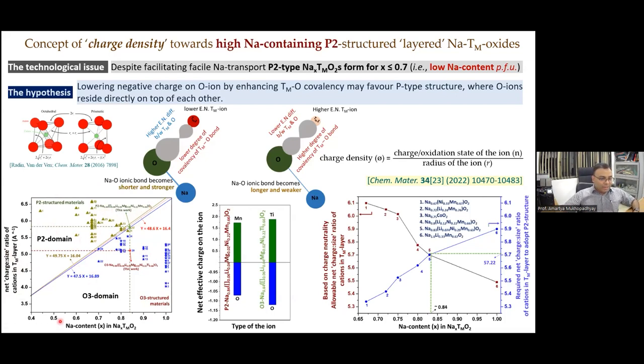And we found that for the same sodium content, a higher charge to size ratio leads to a P2 type structure and a lower charge to size ratio leads to an O3 type structure, which agrees with our hypothesis. Now, again, DFT calculations by Professor Abhijit Chatterjee's group revealed that if we design two materials which are more or less the same in terms of the composition, except that manganese 4+ in one is replaced with titanium 4+ in the other, rest all remaining the same, and even the content of manganese 4+ and titanium 4+ remaining the same.